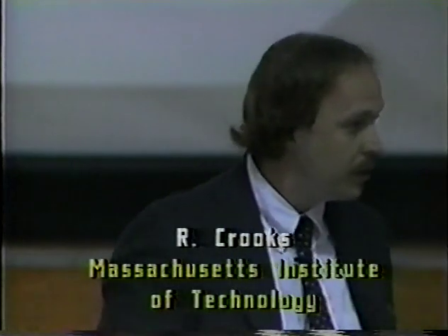No, there's no reason. At the beginning of these experiments, we decided on an experimental design and a goal, and the goal was to mimic the Pons and Fleischmann data as closely as we could. So we chose the middle current density that they had suggested for showing excess heat, which was 64 milliamps per square centimeter. We know that our calorimetry is good enough to see the types of excess heat that they claim for that current density, and so we stuck with that. As our experiments proceed, we'll increase the power and see if we can see changes. But nevertheless, under the conditions that we've reported, we saw no changes, while Pons and Fleischmann and others have reported higher excess powers.